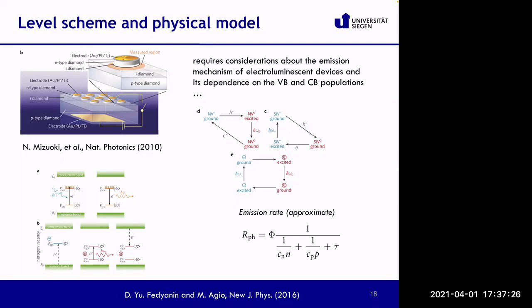So in the situation of holes, you know that the energy scale is opposite to the energy scale of electrons. So if you go up, you lose energy. If you go down, you acquire energy. So then what happens is that the hole, in the capture process, is not going to the ground state, but is going to the excited state. So then you go from a neutral state to the excited state that emits a photon. And then after emitting the photon, the center acquires an electron and goes back to the negative state that was in the original situation. So in this case, you have emission from the neutral state of the nitrogen vacancy. And this has been experimentally observed, while optically, you can equally excite a neutral or negatively charged state.